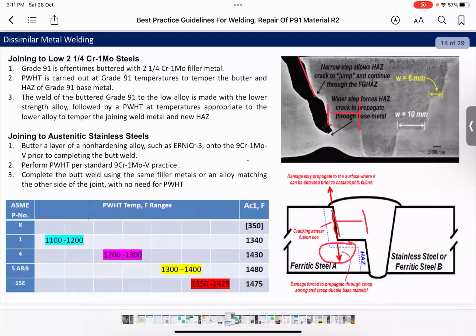So why do we do this? Because as you see in the table, the lower critical temperature or AC1 temperature for P22 or P11 can be lower than PWHT temperature for P91 material, and this can create a problem. We know that we should not exceed this temperature. So this is one of the reasons why we should take care of welding P91 to a different grade, and this is why we use an undermatching filler wire for welding this dissimilar joint configuration.